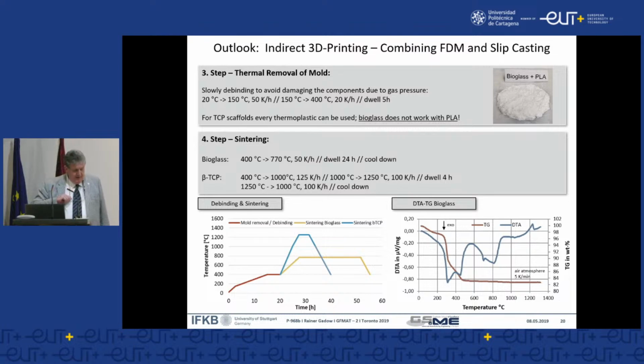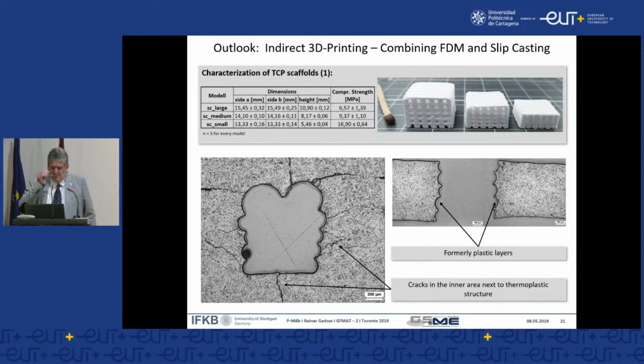At the very beginning, Stefan Esslinger is a guy of my size. I saw him with tears in the eyes. He was completely disappointed when he sintered the first sample of his bioglass bodies, because he was a classic mechanical engineer. He was not a chemist. And the surprise was that the bioglass did not keep its original form and shape. Following the gravity we have also in our laboratories, the powder compact body did collapse. So we had to restart the program again, and then step by step, by the change of additives, by the modification of parameters, at the very end it did work, that also with the bioglass as raw material, we could achieve such samples.